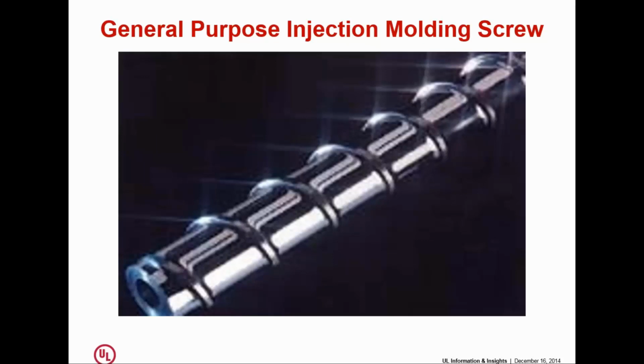I have a colleague by the name of Bob Dre who has worked in the extrusion industry for a long, long time, probably 45, 50 years, and Bob calls this a no-purpose screw. His contention is that the screw that we in injection molding typically use does not do what it's intended to do, which is to produce a homogeneous melt, a melt that is of the same temperature and the same consistency throughout. And if you don't believe that this is the case, all you have to do is try to mold a material like, say, polycarbonate in a color where the color is being applied by adding a color concentrate, and see how difficult it is to produce a part that is free of swirls and free of color variation. That's a visual indication of a lack of homogeneity.